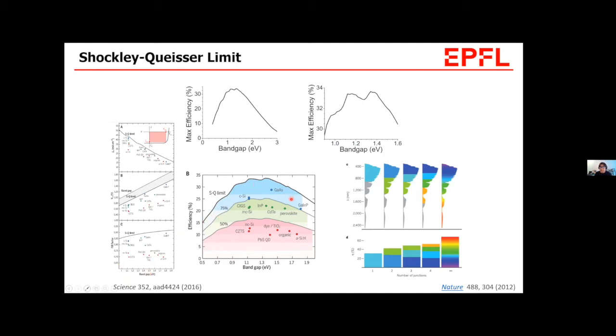We have this Shockley-Queisser limit of efficiency, the black line, for example. When we have a look at perovskite, though this is not the state-of-the-art one, if you think about FAPbI3, which is the state-of-the-art perovskite, having a band gap around 1.5 electron volts, we could expect its efficiency to go over 30%, ideally, according to this graph.